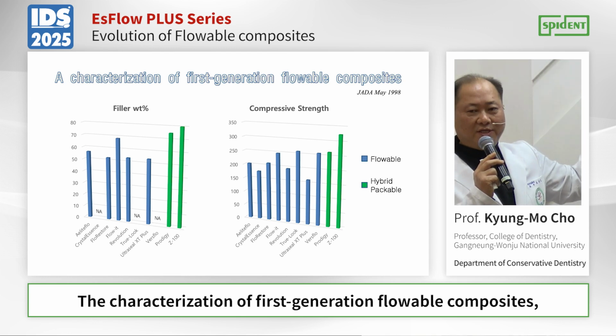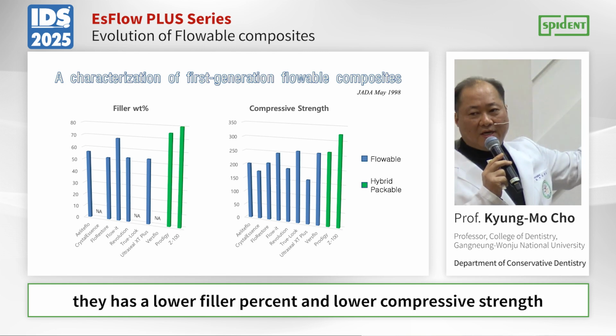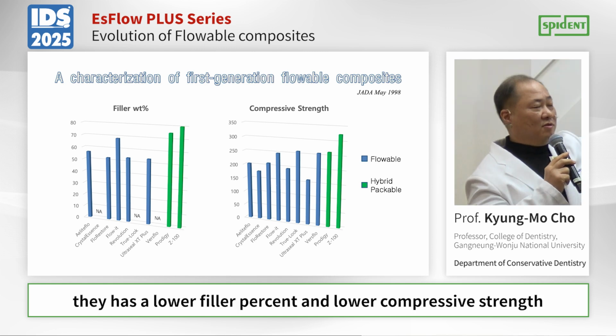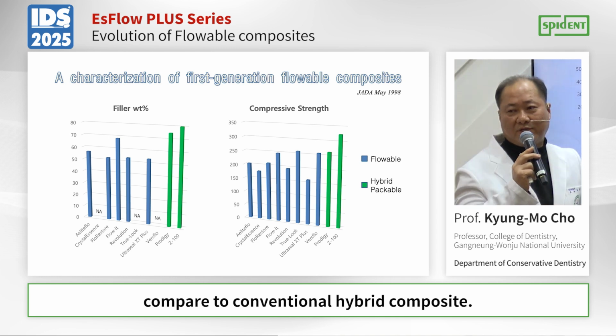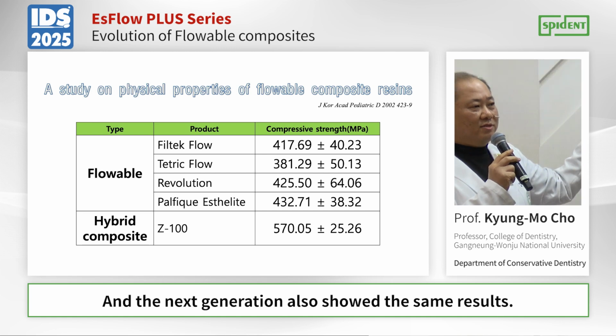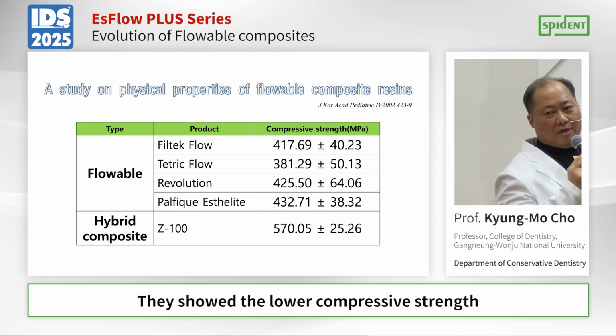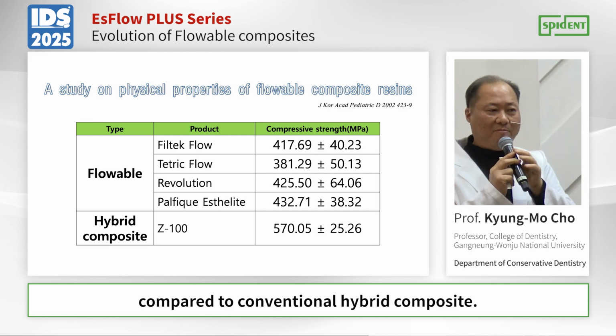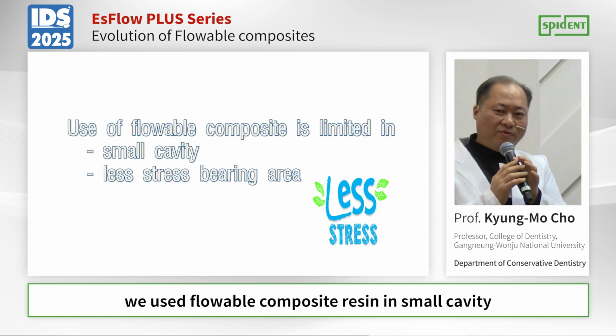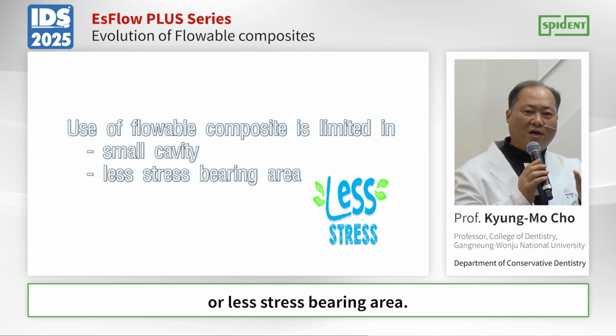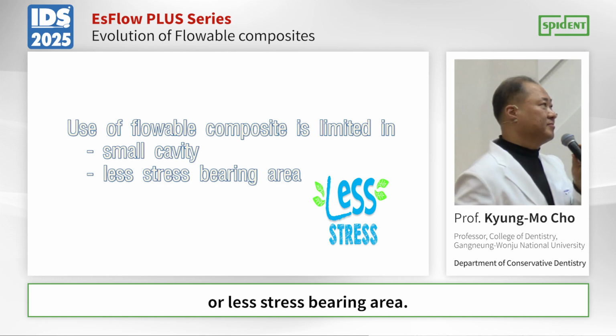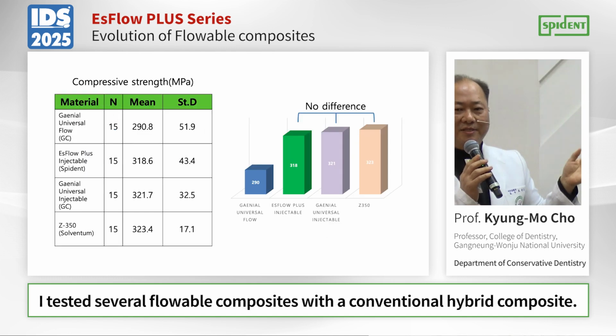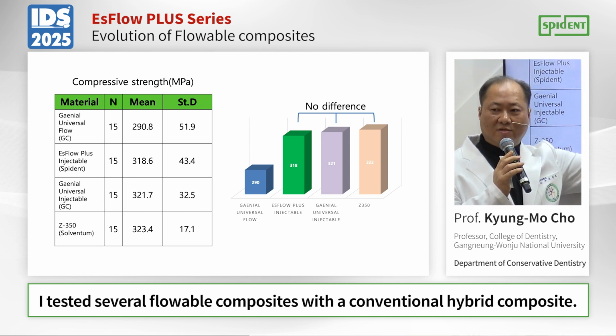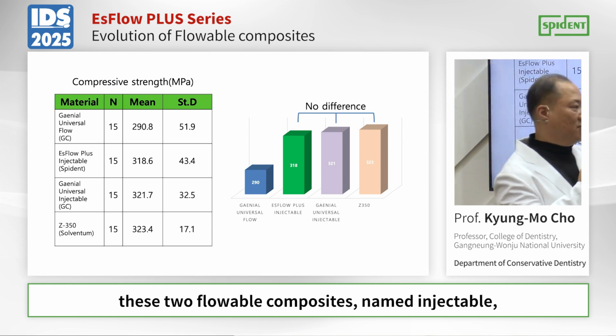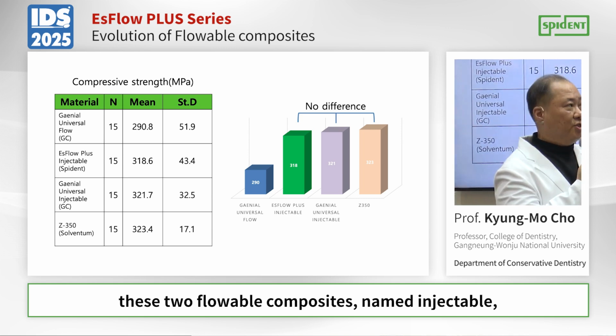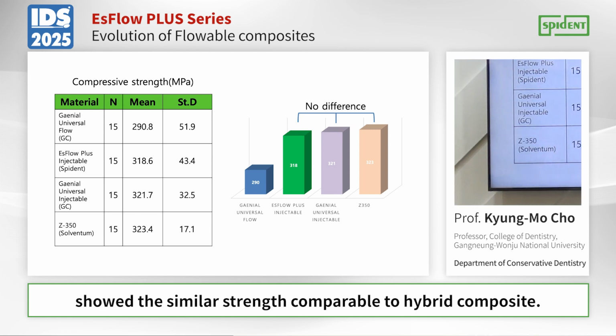As you can see here, the first generation of flowable composite has a lower filler percent and lower compressive strength compared to conventional hybrid composite. The next generation also showed the same result. So we used flowable composite resin in small cavities or less stress-bearing areas. But about 2 months ago, I tested several flowable composites with a conventional hybrid composite. In the result, these two flowable composites, named injectable, show similar strength comparable to hybrid composite.